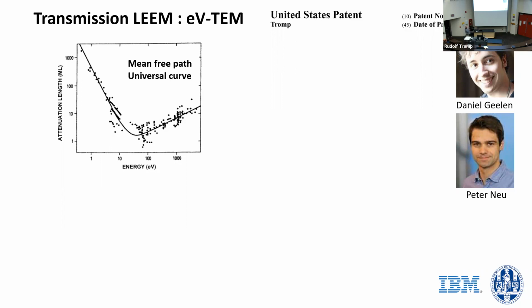Well, here's a plot of the mean free path of electrons. This is called the universal curve. I'll tell you right now that it's wrong, but it shows that below 10 eV or so, the electrons can travel deeper into the solid again, right? Why? Because there's nothing left to excite anymore, basically. You cannot excite plasmons anymore. There's not enough energy. So these electrons can't lose their energy, so they gotta keep going, right? It's a car without brakes. That's the idea.